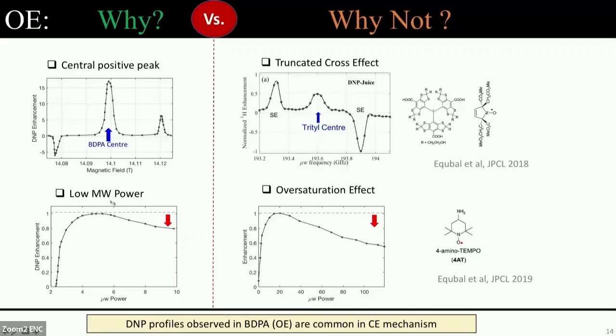But if we closely look at this power profile, after reaching a maximum, the enhancement starts going down. So this cannot be a feature of Overhauser effect. If it is Overhauser saturation, then it should reach a maximum and remain a flat line. But here we see the enhancement starts going down as we increase the microwave power. This, on the other hand, can be an attribute of cross-effect DNP. If we have two electrons, and in cross-effect, since we need to maximize the polarization difference, a microwave power above optimum would lower the polarization difference, because then we would start saturating both the electrons. We won't be saturating selectively at very high microwave power. So this decrease in the DNP enhancement at large microwave power could be an attribute of cross effect.